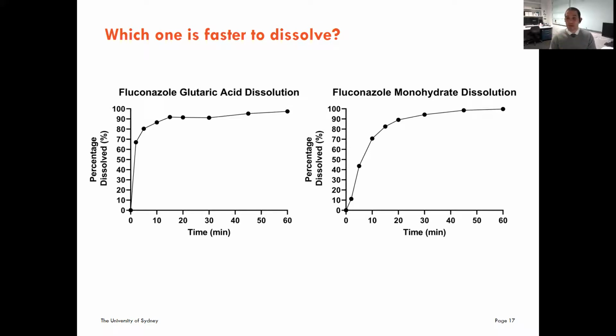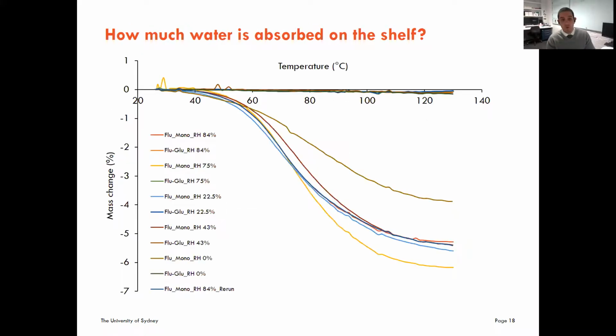It just reaffirmed that potential for those hydrophobic regions, or the better stacking, for it to dissolve and break free a lot quicker than simply allowing water molecules to get through those hydrophilic channels that we saw in the monohydrate. Now, when we look at the stability of our molecule, we're looking at how much water it can absorb into its structure. This doesn't just generally mean bonding into the structure, but it physically means absorbing a water molecule from the air into the actual physical product, whether it be a capsule or a tablet, which can unfortunately cause degradation and a lower shelf life.